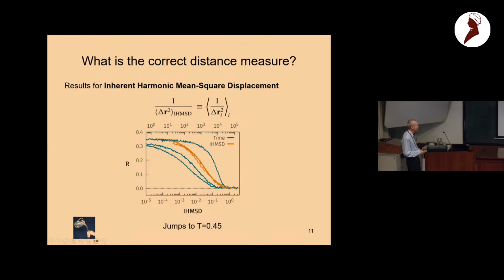These are quite extensive computer simulations going to this temperature, 0.45, and we're jumping from 55 and from 50 and from 40. So this blue curve is the normalized relaxation function for the jump from 0.4 to 0.45 for the potential energy. And we didn't have one from 35 because we couldn't equilibrate at 35.